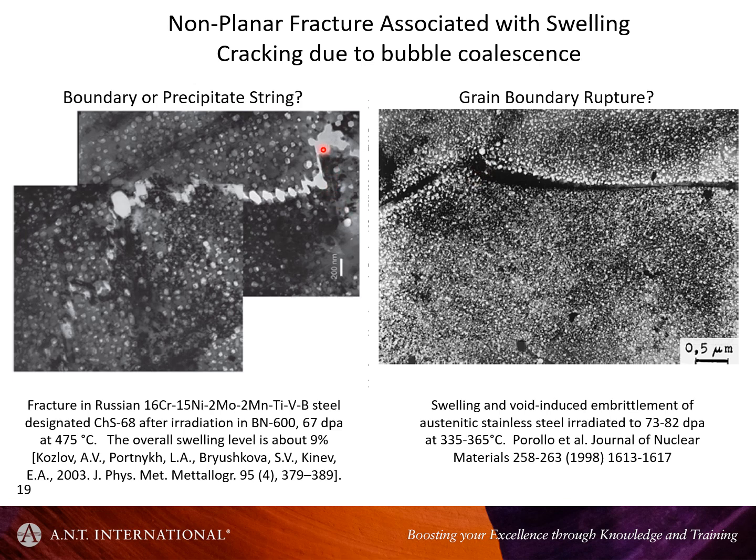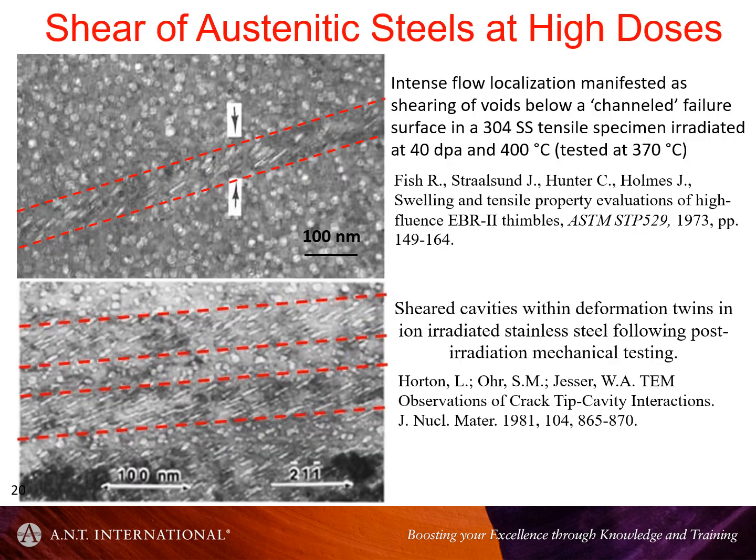But there are other examples where the crack takes a normal zigzag type pattern, as you would expect from a normal ductile failure. But the very fact that you've got these ligaments, thinner ligaments between the cavities, it's not hard to accept that you're going to get some preferential ductile deformation there, and eventually you'll get the ligament failure between certain cavities when they have a certain density.